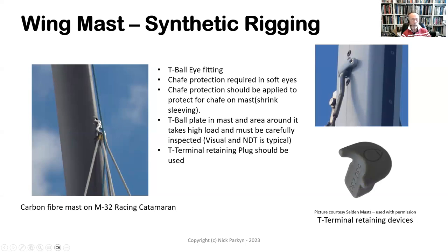Also, this highlights the fact that when you start to use these T-ball fittings, you can use a stopper above the fitting to ensure that the fitting can't come loose. Because remember that when we operate the rigging on rotating wing masts, the rigging is not drum tight because we have to allow for that rotation. And so typically the rigging is tightened with lashings and not with rigging screws. So again, it's very important to ensure that we lock the T-ball fittings.